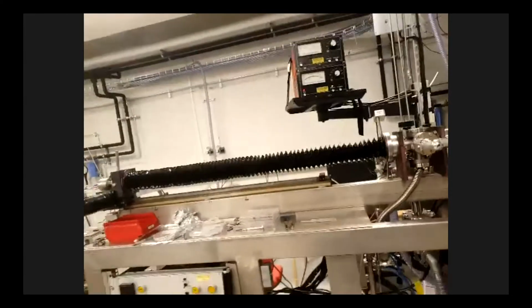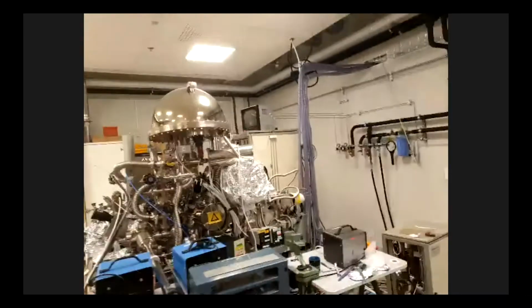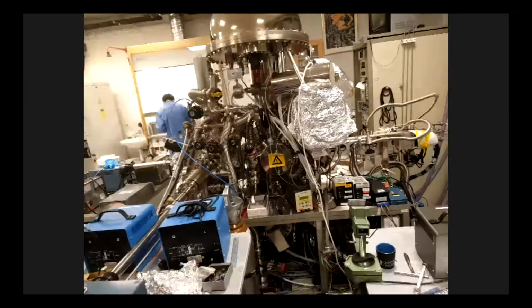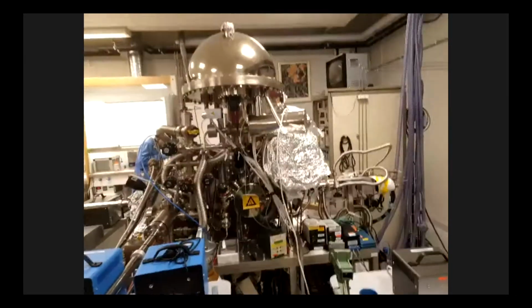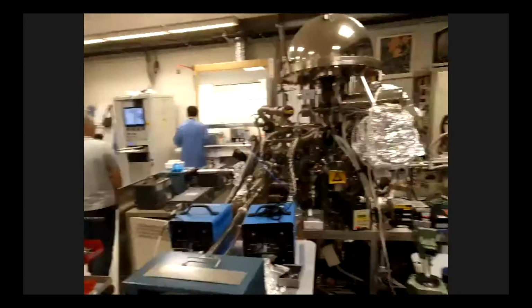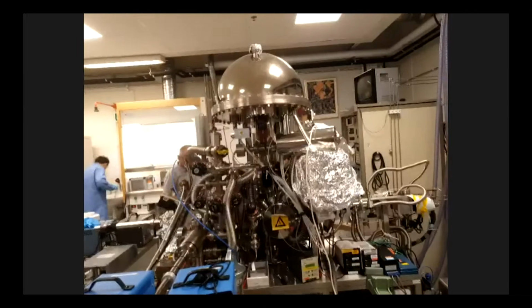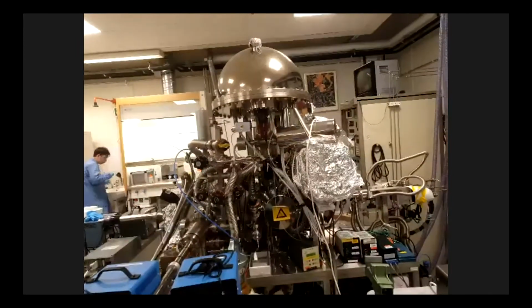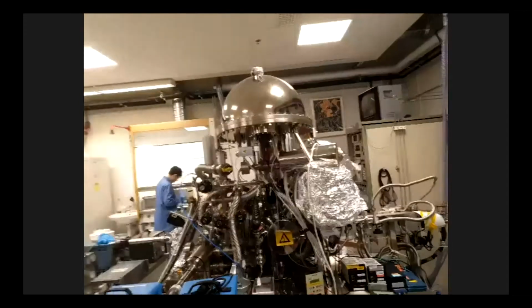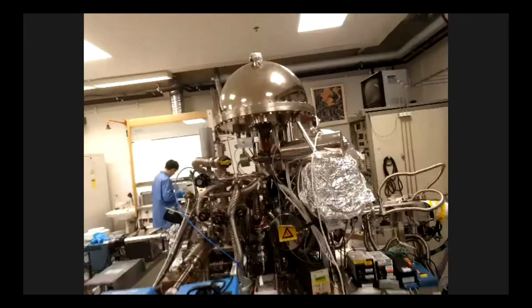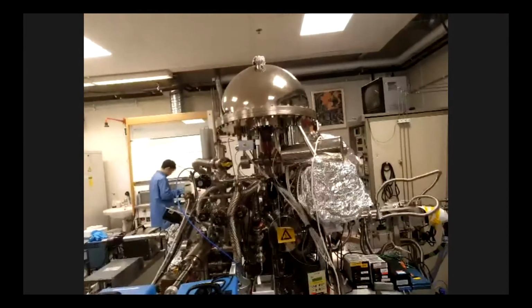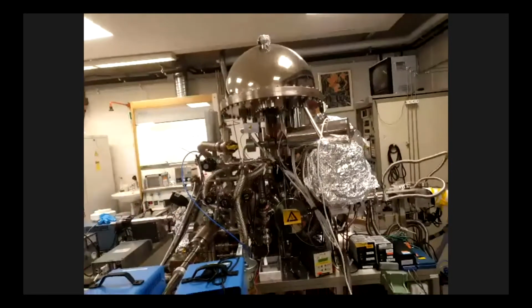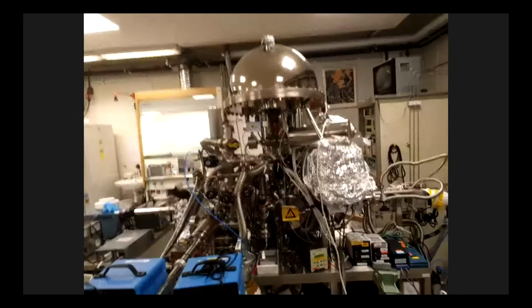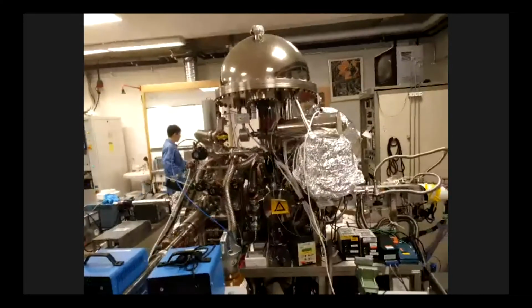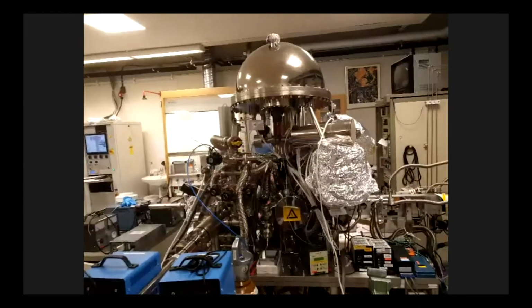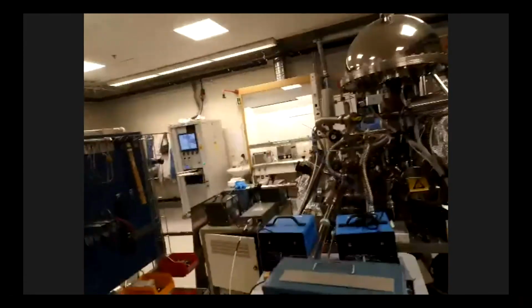There is a trick you can do in the more fancy machine, the Scienta, where we have a so-called flood gun, and then you bombard the sample with a beam of low energy electrons to compensate for the electrons that we kick out. This enables, I would say, a check of the elemental composition, but I personally do not trust chemical shifts, because this electron beam and the sample charging is not uniform over the sample surface, so you get slightly different potentials and broadening of the peaks. Now I'm getting technical, but anyway, you can look at insulating samples here, but it's more limited in what real, or trustworthy, information we can give you.